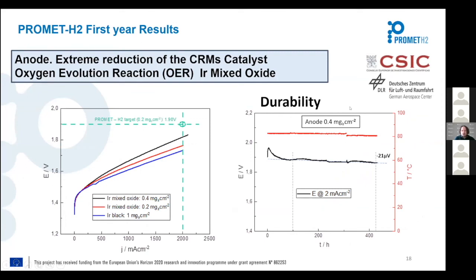Now I would like to show you one of our best results at the moment that we can show. This is a work that was developed by CSIC. And also we cooperated in the preparation of the MEAs and also in the testing. This is a new material, a new catalyst for the oxygen evolution reaction. It's an iridium mixed oxide. And we can see here on the left side, it's compared with iridium black, with 1 milligram of iridium black. It's one of the more active catalysts that we know in electrolysis.